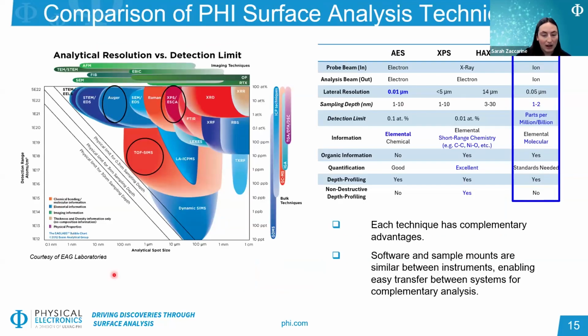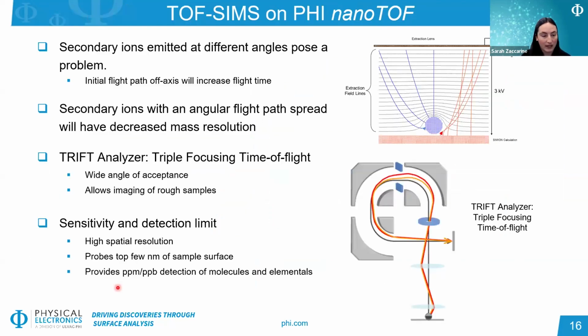So next, we're going to look a bit more at TOF-SIMS. Generally in TOF-SIMS, imaging a rough sample can be challenging. If we look at this example of these extraction field lines on the top right, this is a particle, or you could imagine potentially looking down the nanowire tube. You're going to have ions coming off not only normal to your analyzer, but all of the edges as well, similar to what we talked about with the SEM. This means that these ions will be leaving the sample at different angles and hitting the detector at slightly different times, which can decrease the mass resolution of our signal.